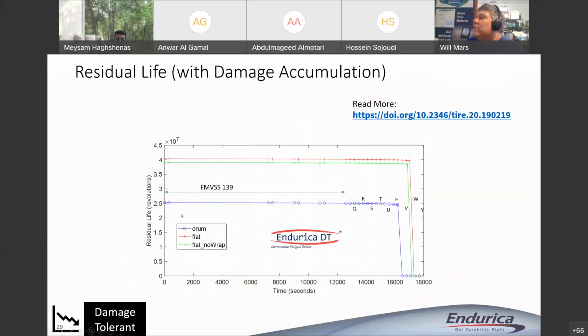And here's kind of the final result when we follow that workflow. What we get is a plot of residual life as a function of time into the sequence of tests in that schedule for the FMVSS and for the speed ratings, right? So if you survive for the first, what is that, 13,000 seconds, that means you've passed the FMVSS 139, and then you can see these are the points where you pass the Q, the R, the S, the T. Now in this case, these models were failing at the H and V speed steps in the procedure.